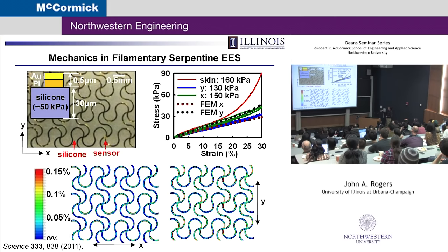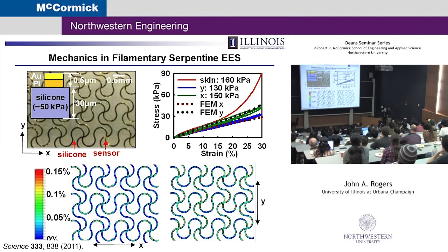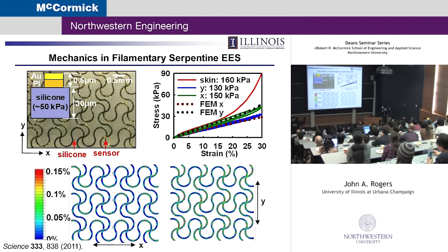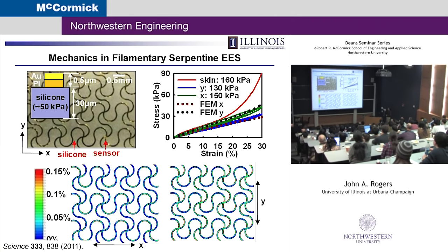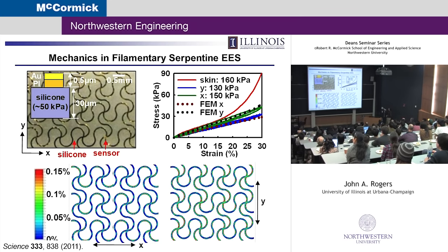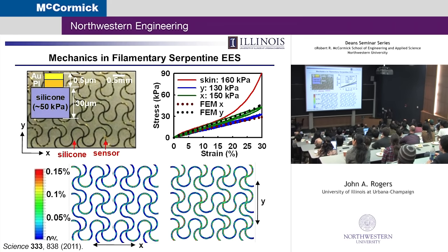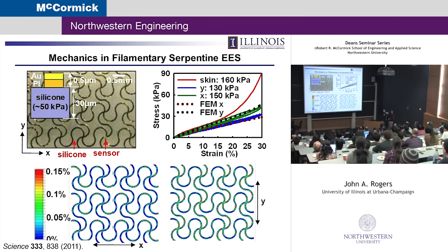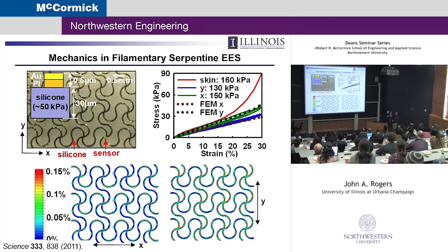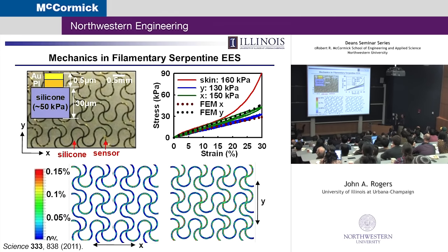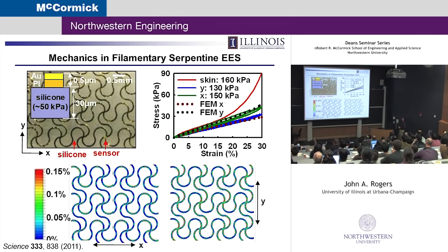Here are stress strain curves measured in an integrated circuit with that type of configuration for the circuit itself, the finite element modeling results over here, and skin. This is actually pig skin. It's pretty close to human skin. It's about 160 kilopascal over a strain range up to about 20% tensile. It starts going nonlinear, and there's an irreversible behavior up here, but linear up to about 20%.